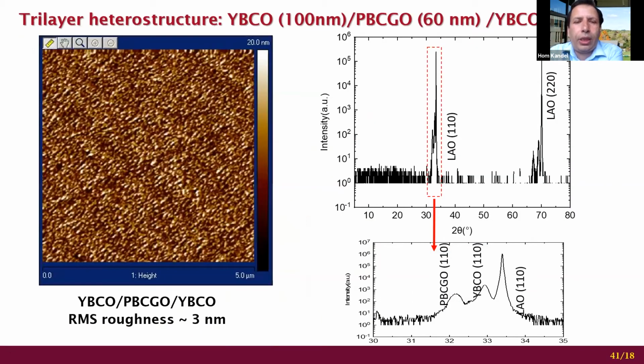We are working with growing tri-layer with YBCO 100 nanometer at the base as the base layer, then PBCGO 60 nanometer in between, another YBCO on top. So this is a tri-layer structure, and we are also working to optimize this thickness down to 1 nanometer. But obviously there are different options.